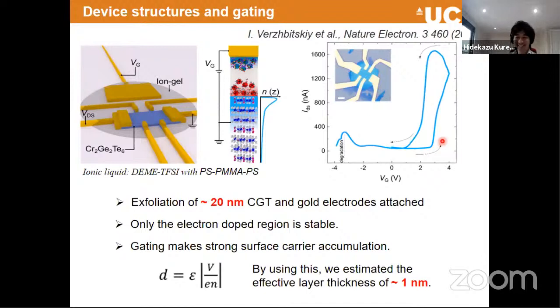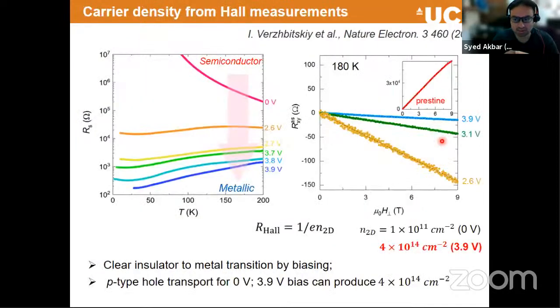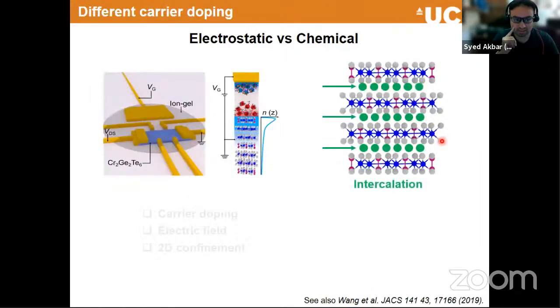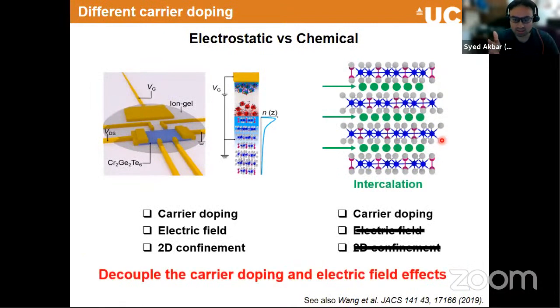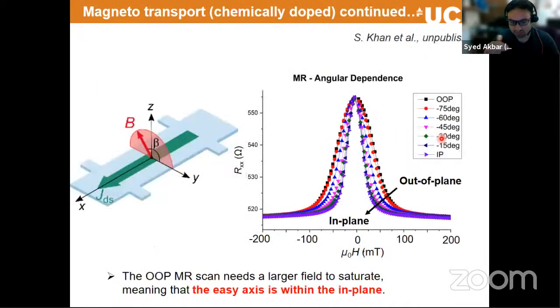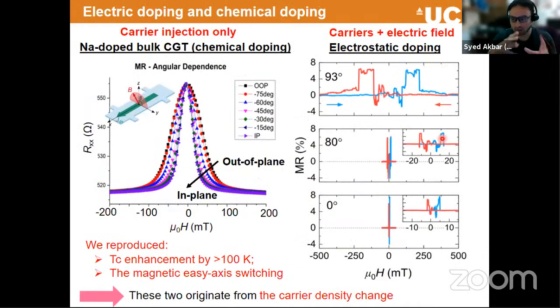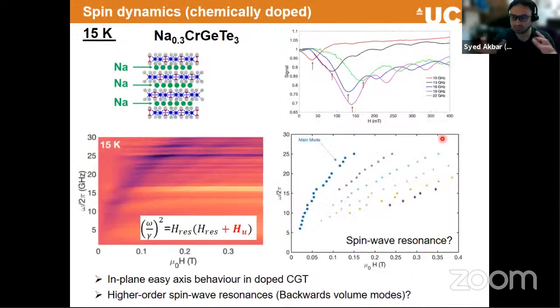Okay. Just a quick question, because you compared two different ways of doping. You did the gating and also the chemical doping. Your main aim was to eliminate the electric field and the confinement, and to identify how that plays a role. But in terms of the sodium, where you dope for 1.0 and 0.3, is that the same amount of electrons for chromium? Is that comparable to the gate doping? You said for the gate doping, you had 25%, and for chemical doping, I'm not too sure how much that changed.